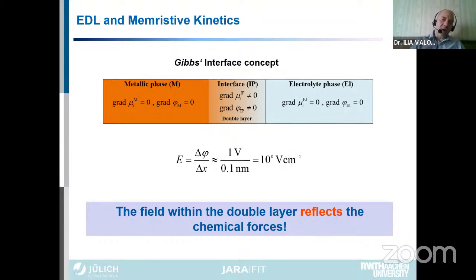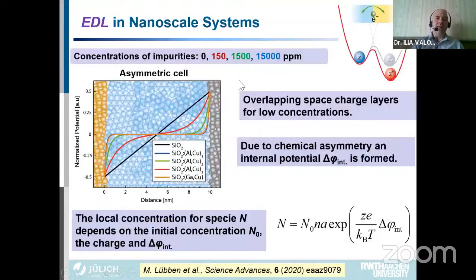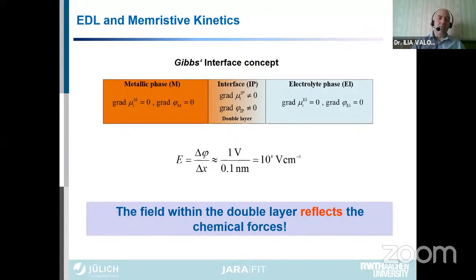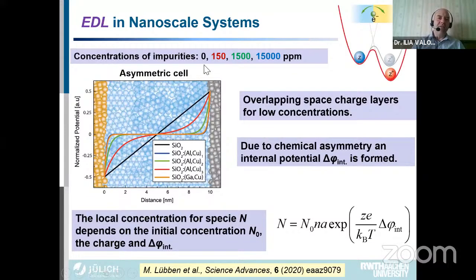So what happens when we take this interface and make it our electrolyte? This is actually what we mostly make with memristive devices. We don't have a classical situation, but we have this situation. We take the interface, and our interface is, so to say, the electrolyte. And it depends, of course, on the concentration. So it depends how many ions we have within this interface. If we have a few ions, let's say black is zero. Of course, these are calculated values, so absolute zero you cannot have, or 150 ppm.